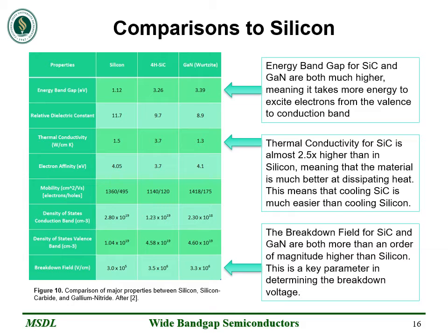Another thing that we'll notice is down at the bottom of the chart is the breakdown field. So this is the critical electric field. Now for silicon, this is about 3e5 volts per centimeter. But for the wide bandgap materials, we can see that we're roughly an order of magnitude higher. And this is a key parameter in determining the breakdown voltage in devices. One final thing to touch on from this chart is the thermal conductivity. For silicon carbide, we can see that it's almost 2.5 times larger than that of silicon, which means that silicon carbide is much better at dissipating heat, and so the cooling requirements for silicon carbide are then significantly lower.